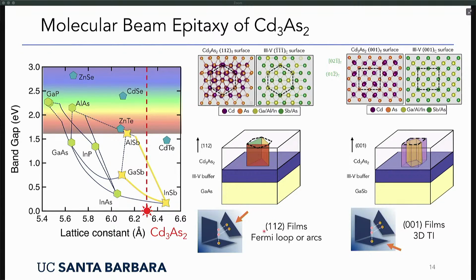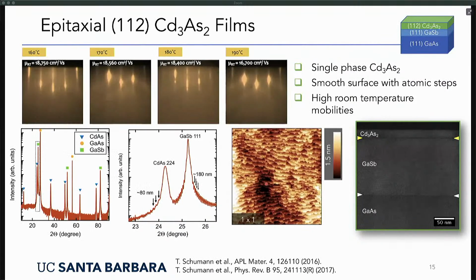So just to point out again, we'll talk about these two orientations, 001 films and 112 films of cadmium arsenide. 001, as I mentioned before, is the one where we do not expect these Fermi arc states, because the bulk nodes project onto a point under the surface, versus 112, which is one of the surfaces where we would expect these Fermi arc type of states. So there's a difference in the type of surface states that we would expect for these two growth orientations. So it's very suitable to look at differences in orientation and how they matter in the electronic and transport properties of cadmium arsenide thin films.